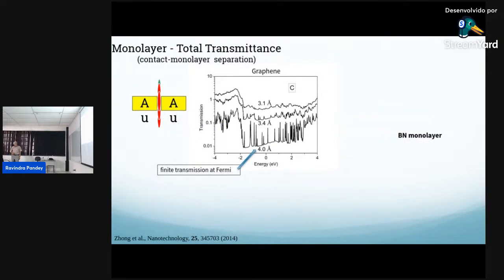So you can see here, we are again looking at this graphene, and now we are varying the contact versus this monolayer separation. So this is what we have, 3.1 angstrom at the equilibrium spacing. I increased to 3.4 and then 4.0. This is the Fermi level at 0. So you can see here, by weakening the effect, the transmission goes down, but graphene is a zero-gap material, so we have to have a finite transmission.